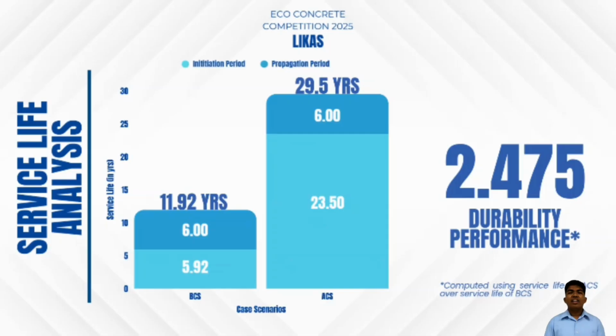Here's the breakthrough. Our alternative mix outperformed the base case by a factor of 2.475. While the base case lasted just under 12 years before failure, the alternative mix delayed corrosion initiation to 23.5 years, achieving a service life of 29.5 years.